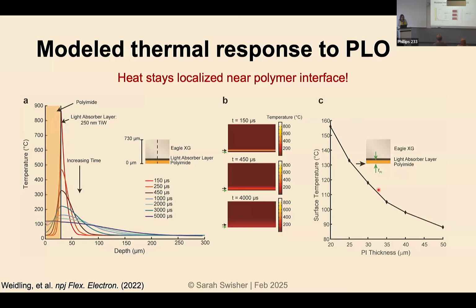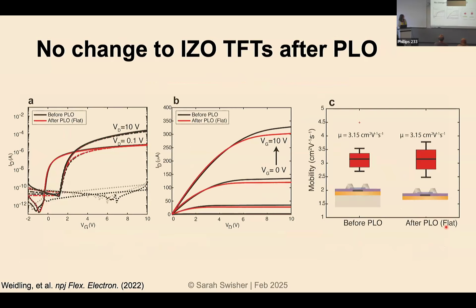And then the other thing we looked at was how the thickness of the polyimide matters, right? Because basically what that's doing is providing the thermal buffer between your ablation and your device layer. And so the thicker the polyimide layer is, you can make sure that your device temperature actually stays even lower if you want to. So what we saw is that when we fabricated these devices, we tested them before and after the liftoff. And you can see that these are basically falling right on top of each other.